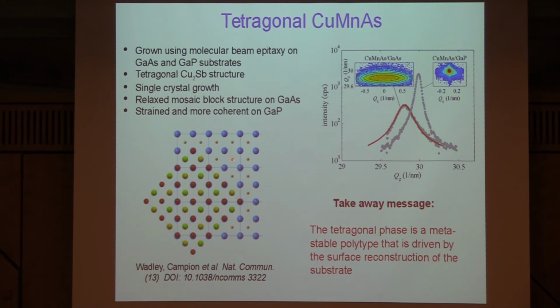And this is how we believe the structure grows. So it basically rotates by 45 degrees to the principal axes of the gallium arsenide. There's the gallium arsenide below. This is the copper manganese arsenide on top. It's rotated by 45 degrees and fits pretty well.